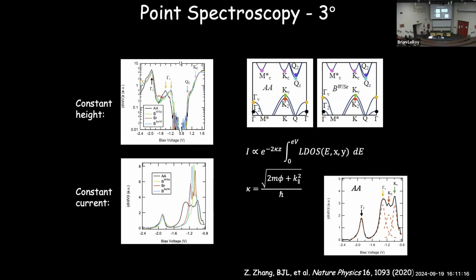Unlike graphene, which had a pretty simple band structure with just this single X, here the band structure is actually fairly complicated. There are lots of different maxima occurring at different momenta here. There's a couple of different bands in the conduction band here, another one slightly offset, a third one here. The band structure is complicated, and that means that when we measure the density of states as a function of energy, there are lots of little shoulders and bumps in here. And those each correspond to hitting each one of these different levels as we change the energy.